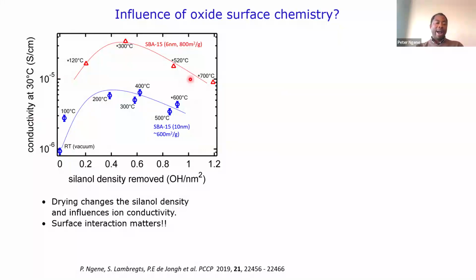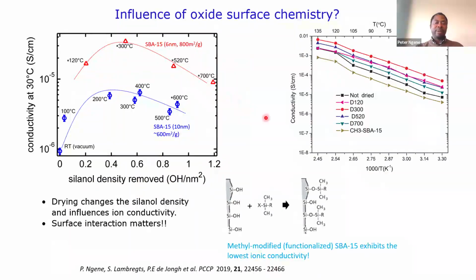If you now begin to dry the silica more, then you have condensation of the silanol groups, so you have less silanol groups on the surface. Because we're removing so much of the silanol groups, we do see that the conductivity decreases, because our active material doesn't have enough surface groups with which it can interact. So this is just a consequence of our understanding from this X-ray Raman scattering.